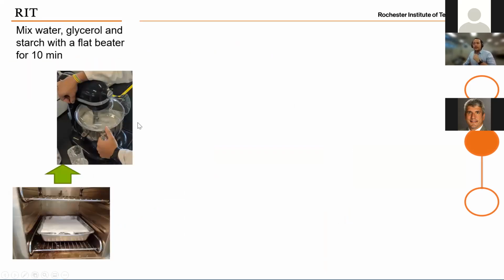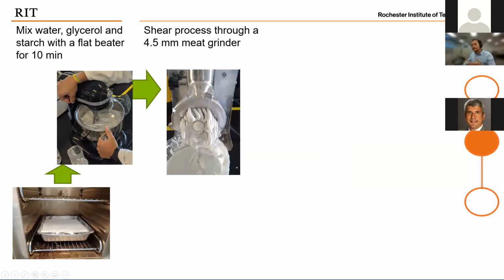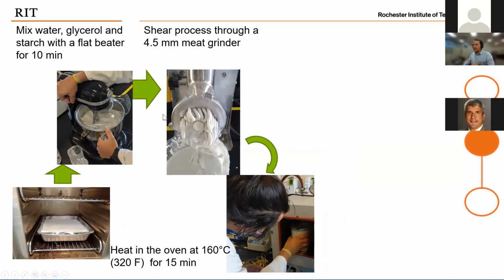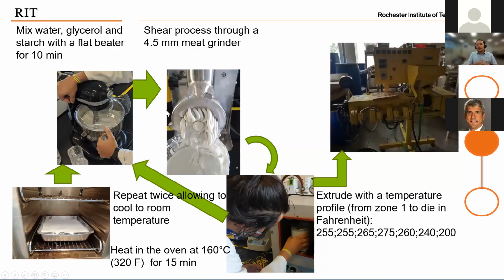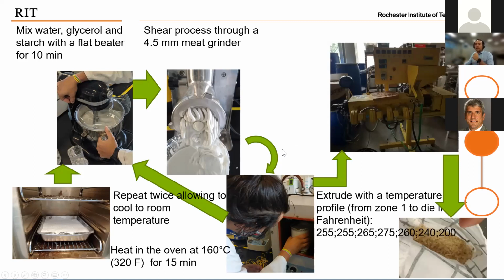So the way I made it is first we dried the starch, and then we mixed it with water and a little bit of glycerol for 10 minutes. Then we put it through a meat grinder, and then I put it in an oven for 15 minutes. And I repeat this twice. After the third time, I can put it in a single screw extruder with a temperature profile that goes from 200 Fahrenheit to 275. The 200 is especially important at the exit, so it doesn't bubble and we don't lose extra moisture. In the oven, I have to mention, it's covered so we don't lose moisture. And after the extrusion, we can pelletize it. We were able to produce pounds, even kilograms of the material, and get it ready for the prototype making.